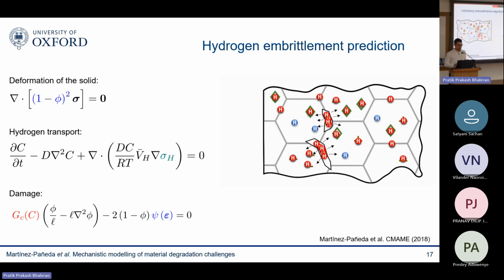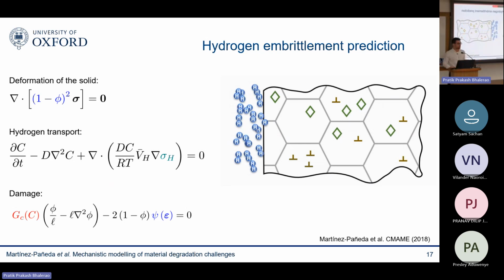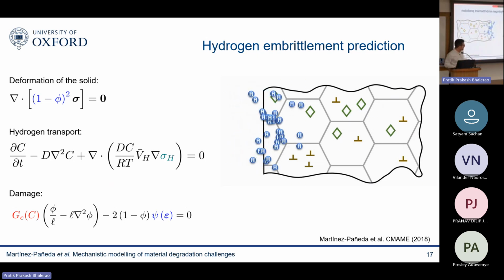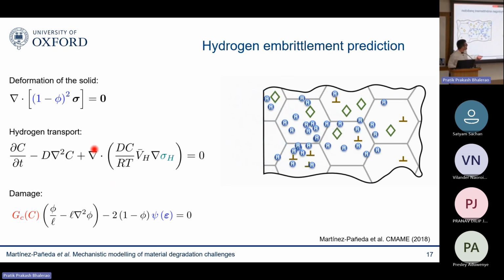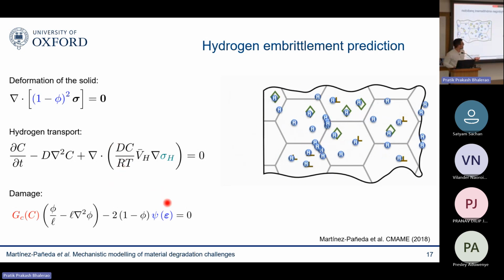So if you wanted to model this, the simplest way you could think of is using phase field technologies. We could think of solving a three-field problem. So you will solve for the deformation in the material, the equation I showed you before, the hydrogen transport equation, and then the damage. And I'm highlighting here some of the coupling.